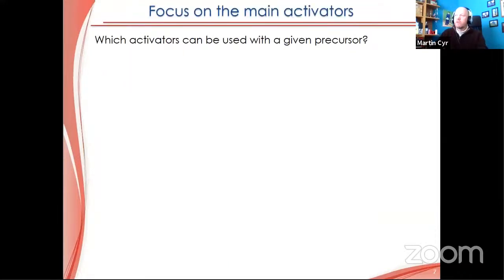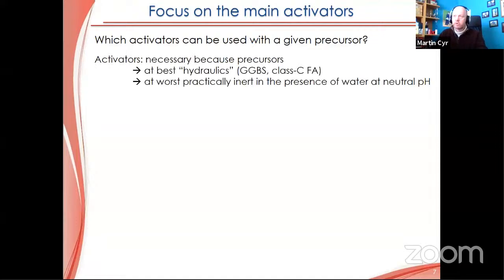So in terms of activator now, what kind of activator can we use with a given precursor? Activators are usually necessary in these kinds of mixes because at best our materials are some kind of hydraulics such as GGBS. If you put water in GGBS and wait a long time, it will probably set because the glass will dissolve a little bit. You have a chemistry involving calcium, meaning that you will probably have some reactivity, but you have to push this kind of material a little bit.